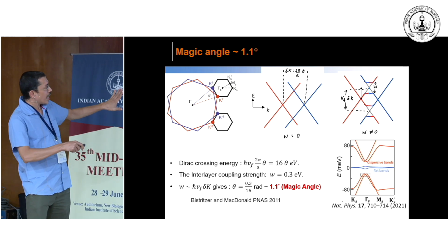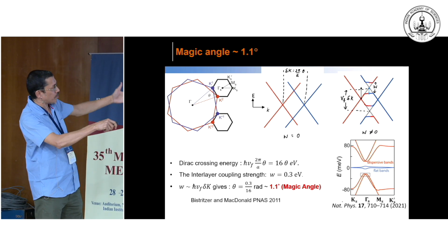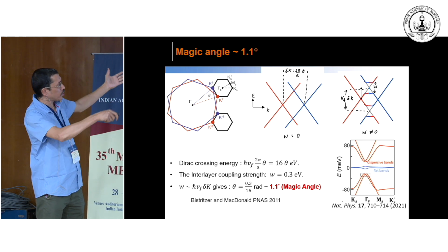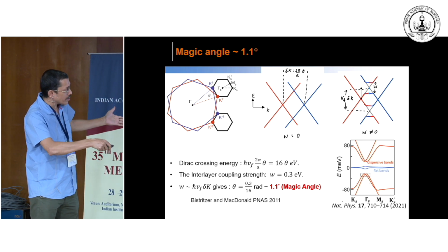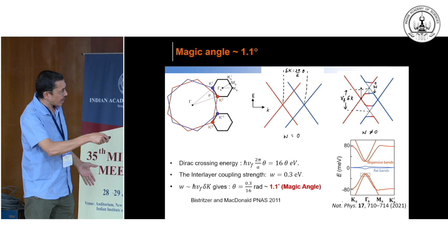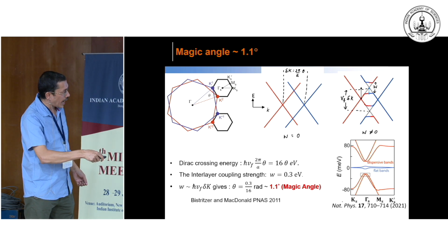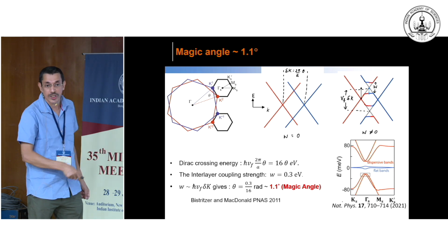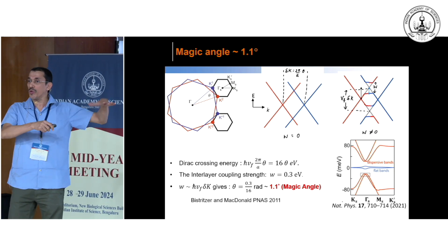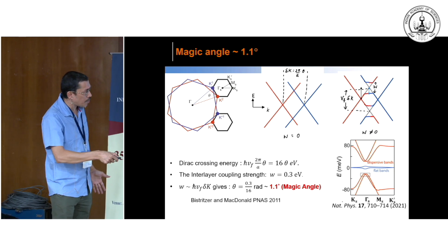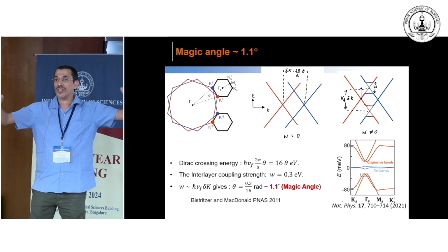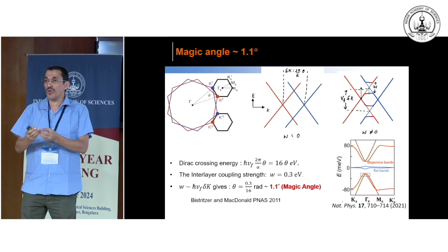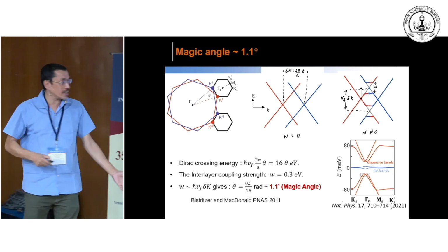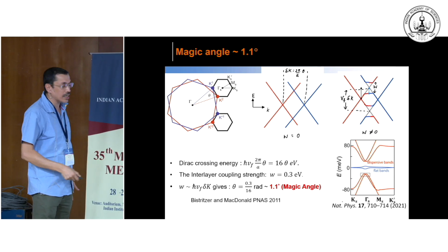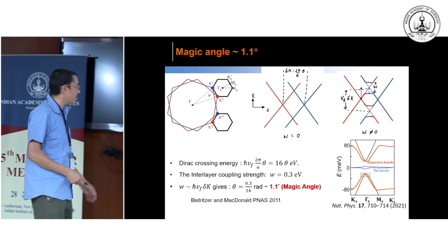But the point is that in original graphene, you have these linear dispersions which go to large energy scales, of the order of 1 eV. But at this 1.1 degree magic angle, you see there is engineering of the band, and you have a tiny band at low energy, a completely flat band, separated from the high energy dispersive band by a band gap. So that is the unique thing about the system, that you can get a flat band, where flat band means your energy is almost not changing with the momentum. Although you are changing the momentum, the energy is not changing, and the width of this band is typically of the order of a few tens of meV.